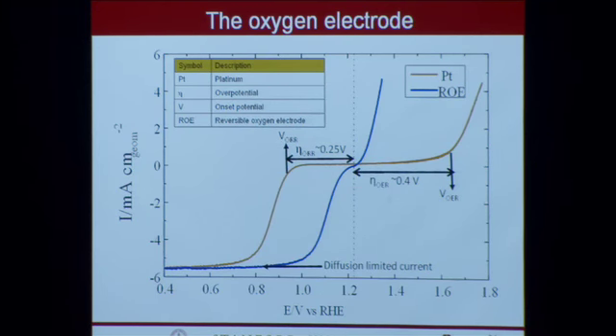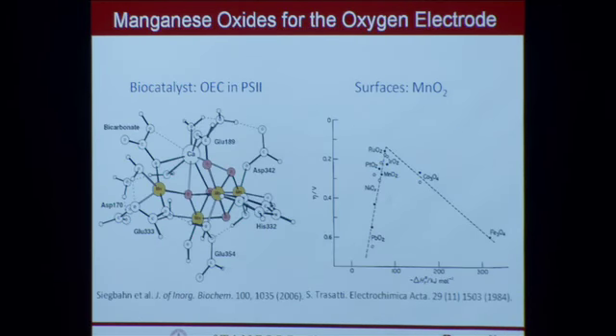So we're looking for a bifunctional electrode. That's really what we're after. We'd like to develop a bifunctional electrode that can do both of these reactions efficiently, and that is exactly what this blue line represents. That's a reversible oxygen electrode. It means that right here at this equilibrium point, you just go a little bit to the left or a little bit to the right, and you're going to get oxidation on one side and reduction on the other, as opposed to, say, platinum, where you have to go significantly far from the equilibrium potential in either direction to get either reaction to go.